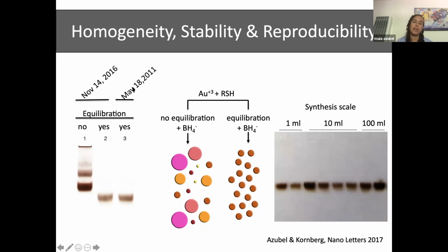And as you can see, I put the dates here just to mention two points. The first one is that the synthesis is reproducible. I was able to make the same synthesis 5.5 years later, and I got the same product. But also, this product is very stable. The sample that I made in May of 2011 was in my fridge, and when I ran the gel, it looked very good. The other thing that is important to mention about this synthesis is that sometimes everything works well on a small scale, but then when you try to scale up to get a lot of clusters, everything goes down. Fortunately, when you do this trick of the equilibration, the synthesis is very stable and very reproducible for different scales.